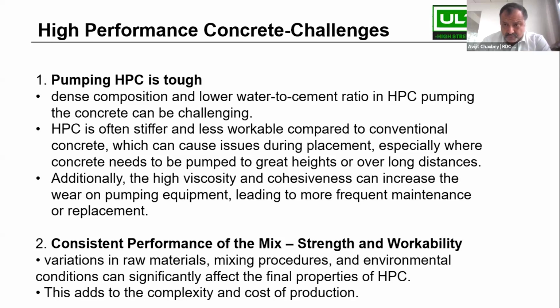And to get the required strength, you have to reduce the water cement ratio. If you see the old mix design code IS 10262, it had 6 graphs, A, B, C, D, E, F, and for the same water cement ratio, a higher strength cement would give a higher strength compared to a cement which has lower strength. Naturally, a high strength cement would end up giving the same strength with a very low cement content or a higher water cement ratio. Now, this is the challenge. Earlier, when we did not have a requirement for such a huge quantum of high strength concrete, we did not have the problems of pumping to a high-rise tower or of very viscous concrete.